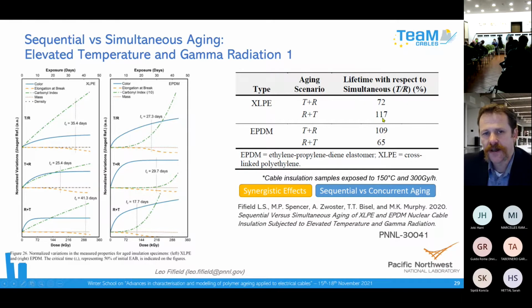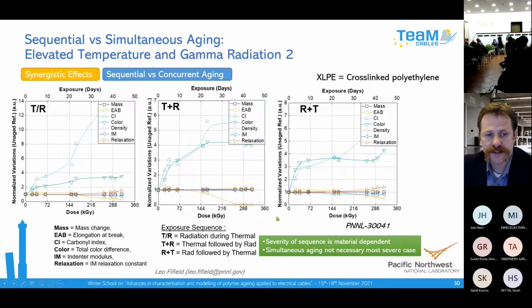In some cases, we saw that the sequential exposure was more severe than the simultaneous exposure that you might see during a cable's service lifetime in the plant. And then sometimes we saw it was less severe. So you have to look at the details of the material to make those predictions. The conclusion is that the severity of the sequence of exposure is material dependent. One of the concerns was that in a plant, these cables are going to get exposed to gamma and heat at the same time, whereas in accelerated aging you have one after the other. If the simultaneous exposure is more severe, then we are overestimating lifetime, and we're going to have more failures than we're anticipating. But one of our conclusions was that's not necessarily the case. In some cases, the simultaneous exposure was actually less severe.